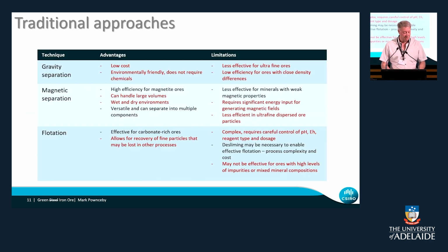So traditional approaches work well in some cases. So gravity separation has advantages, and we use that all the time. We should be able to separate some of the really high-grade material in the lump by gravity. It's less effective for materials where there is really close density. There's not a great density separation. So you imagine goethite particles that go all the way from a nice clean goethite to a really altered goethite. Their densities are going to vary all over the place. So it's really difficult to actually get that split and say, get into a clean goethite versus a dirty goethite concentrate.